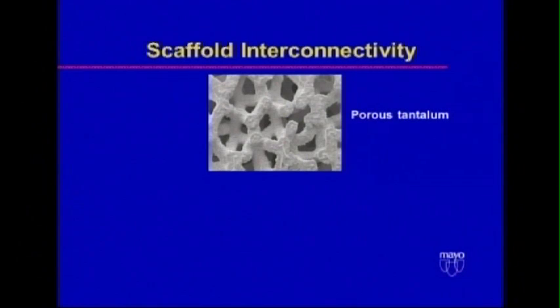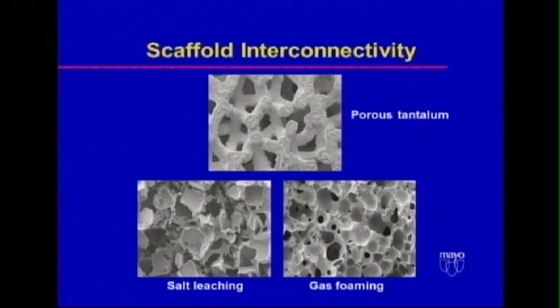So I wanted to put a couple of these in to show. We work with polymers, that's our bias. But there's lots of other ways to get the job done that you want to do. And our hip and knee surgeons are very happy with this porous tantalum. There's also another one on the market that's a porous titanium alloy. Two different companies make them, and I'm not sure which one, if either of them, they prefer. But if you see the salt leaching and gas foaming, we go from this very regular dodecahedral structure in the porous tantalum to very irregular.